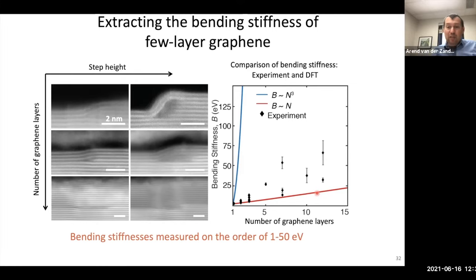The difference between these two, that blue line would be equivalent to having a book, right? Where if you try to bend it, it's super stiff. And that's because the layers are interacting, and so stiffness gets transmitted between the layers. However, what if the layers are allowed to slip with respect to each other? So now if I bend this much thicker stack of paper, what I find is that I can bend it really easily. And what you see is along the right-hand side, maybe it's your left-hand side, the reason why it's bending really easily is the bottom layers are slipping and going out with respect to the top layers.